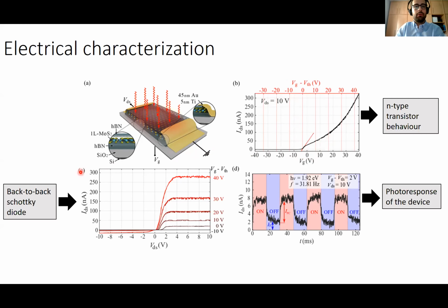In figure C, we have the IV curves of the device for different gate voltages that are indicated here. And we have that the device has a saturation for high source-drain voltage. This current saturation is provoked because we have Schottky contacts, and this gives us the behavior of a back-to-back Schottky diode. Also, we observe that the current saturation is not symmetric, and this is because the heights of the barriers of the Schottky contacts are different, so we have an asymmetry.